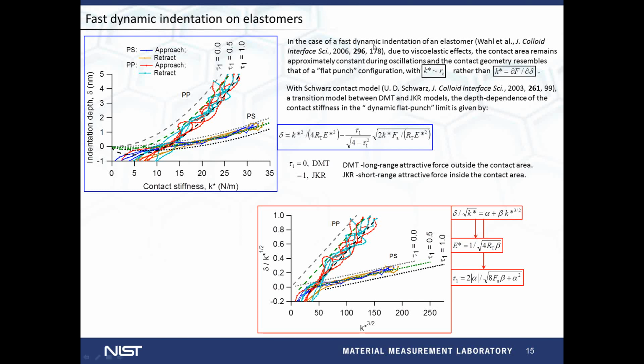Also, what we use in this analysis is that, as was shown, in the case of a fast oscillation indentation, the viscoelastic effects prevent the peripheral variation imposed by the oscillation onto the contact area. So in this case, we have more of a flat punch configuration with the contact stiffness proportional to the contact radius rather than the slope of the force distance curve. With this assumption of the flat punch configuration in the Schwarz contact model, we calculate the contact stiffness versus indentation depth, and the curves are plotted here, the dash and dot point curves, along with some measurements for each of the materials. We see a very clear separation between them.